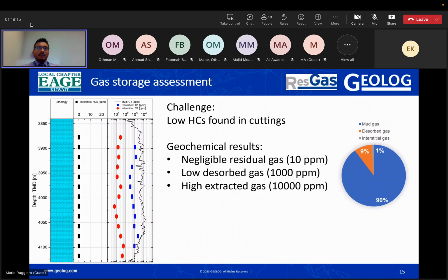We have, for example, this case. We have carbonates. We found a high extracted gas, in the range of 10,000 ppm in the mud gas. And then we analyze the headspace and the residual gas in the pores. And we see that we have a low desorbed gas in the headspace, 1,000. Okay, it's not very low, but it's tenfold lower than the mud gas. And basically negligible residual gas in the pores.